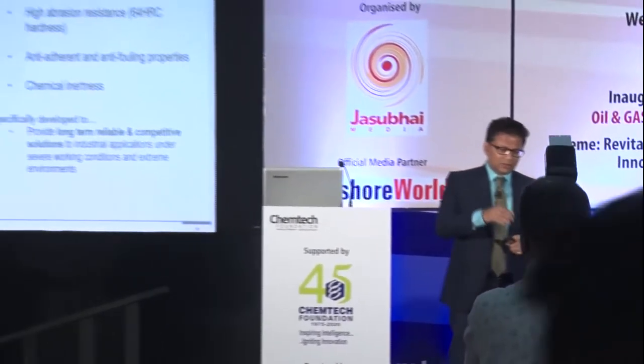So what is Tubacoat? I'm going to take you through what Tubacoat is, what the properties are, and why it works for the applications I mentioned. It has outstanding corrosion resistance in any media and any thermal conditions, whether it's hydrochloric acid or sulfuric acid, or temperatures up to 800 degrees Celsius. It has very good abrasion resistance because the hardness is four times your base substrate, whether it's austenitic steel, carbon steel or Hastelloy. It has very good anti-fouling properties because the surface is as good as a mirror, without any roughness. And it's chemically inert, so it prevents the side reactions that promote the coking reaction. So I'll take you through that.